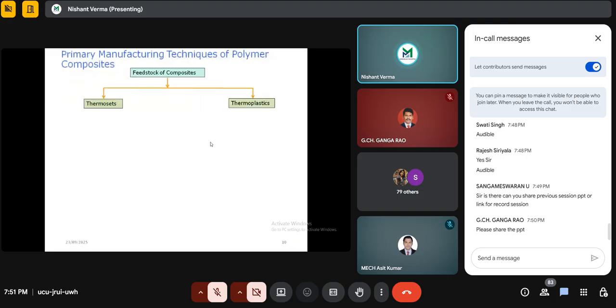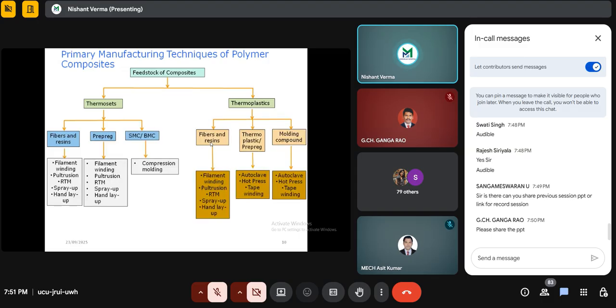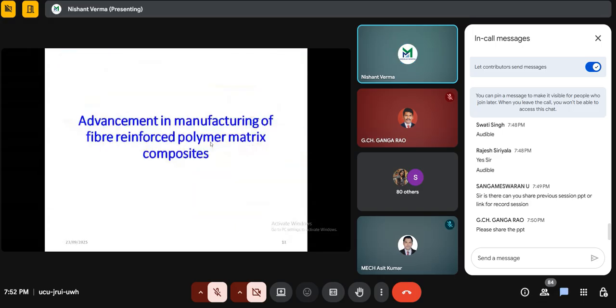So there are several processing routes for the polymer as well as the composite. In case of thermoplastic, we can apply the direct pressure to the matrix material, while in case of thermosetting, as you already know, the raw material mostly comes in the form of resin. So how can anyone apply direct pressure on it? Indirect pressure is required. How can indirect pressure be applied? Either by gas pressure or by vacuum pressure, while in case of thermoplastic polymer, the direct pressure can be applied. After that, I would directly come to that new area, that is microwave assisted compression molding.